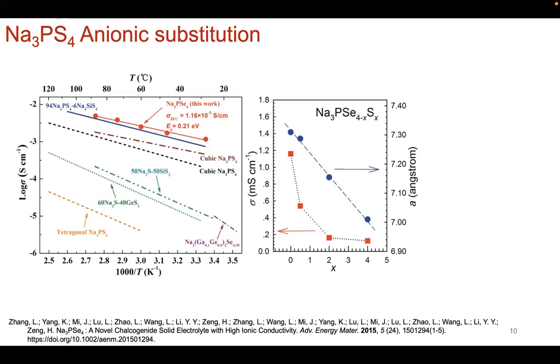Typically, when we think, okay, you're increasing the disorder, that increases the intrinsic ion conductivity. But once you put it in with sodium or whatever metal or the high voltage cathode, then there's going to be decomposition at the interface. And depending on the substitution element, that's not always favorable. Because what you have to balance is, yes, the intrinsic ion conductivity might be increasing, but the thermal decomposition and the reducibility of the cation that you're putting in might actually have detrimental effects, as in inducing SEI and decomposition products that are not beneficial to transport of ions across the interface. And sometimes that actually is more important than just improving the ion conductivity.